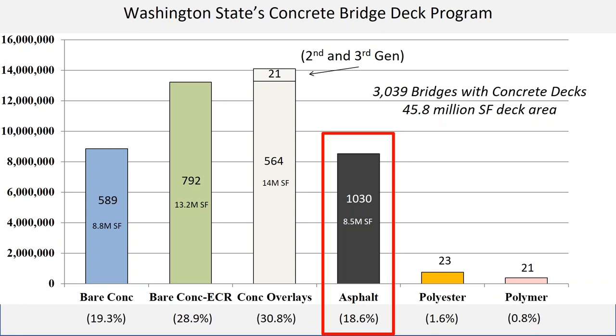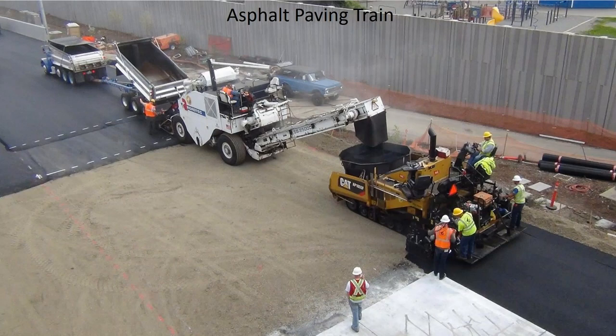So as far as asphalt overlays, we have over 1,000 bridges that have asphalt overlays. And this is kind of a typical paving train. You'll have dump trucks that dump into another piece of equipment that warms up the asphalt and then drops that into the paving machine. And this intermediate piece of equipment is really heavy on those two axles. And so we can't always allow those on bridges.